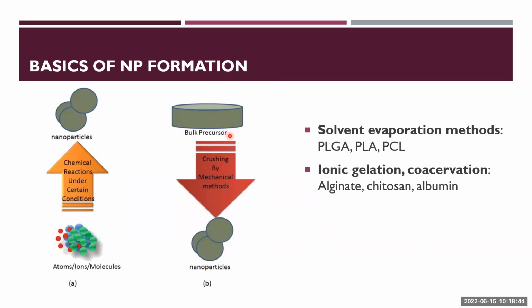If it's a solid, usually it's done by nanomilling, but it's very limited in application. If you want to encapsulate something, usually it's not suitable. Most of these bulk precursors start with a liquid that needs to be separated into small droplets. Then these droplets become nanoparticles. So either the liquid is a solution that you spray, then the solvent will evaporate, leaving whatever was dissolved in the solution as nanoparticles. Or, commonly also, you can make it as an emulsion. Then you spray the emulsion to make nanoparticles, or you evaporate the solvent to make nanoparticles. These are the common methods to make nanoparticles using the second mechanism.